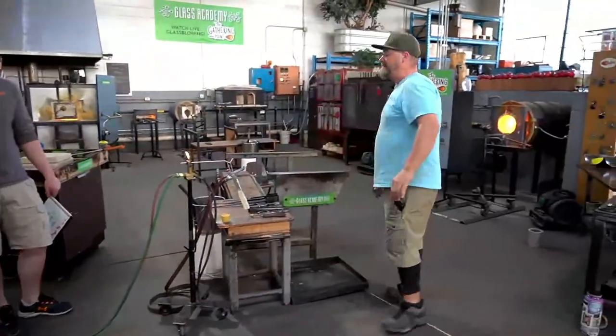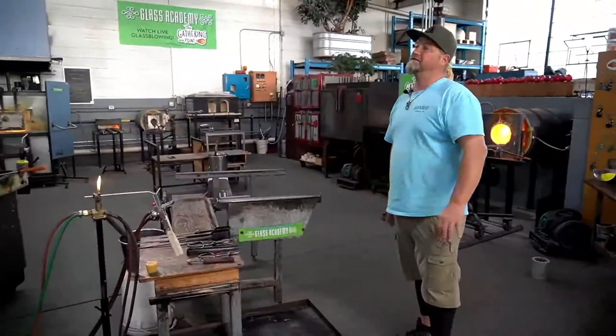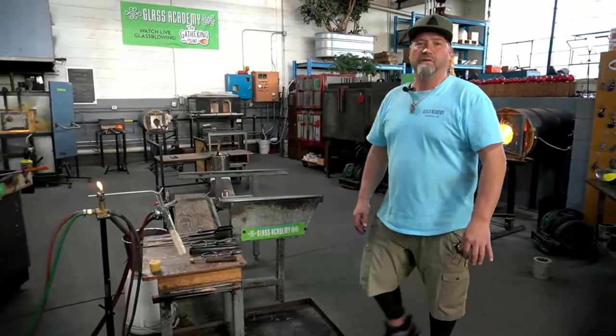The only thing that I think I might need would be the fluffer torch for that dropout when you're doing a vase. So if one of you guys wanna grab the fluffer torch for me, yeah, I got it. Basically, what that means is when I blow a sphere almost, I heat the half of that sphere up and I use gravity and I let the bottom of the vase start falling out and I use the fluffer torch, this big external torch, to heat that section up and it falls out into a beautiful hourglass shape. And then you blow the bottom out more and shape it, punty it up, and finish the vase.